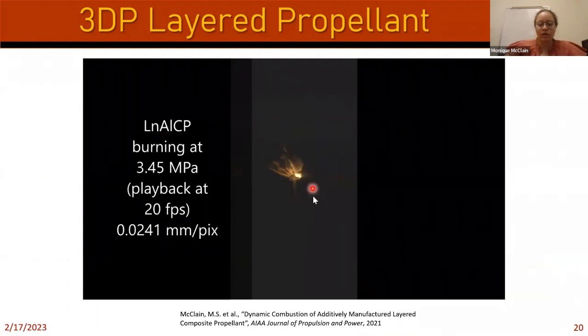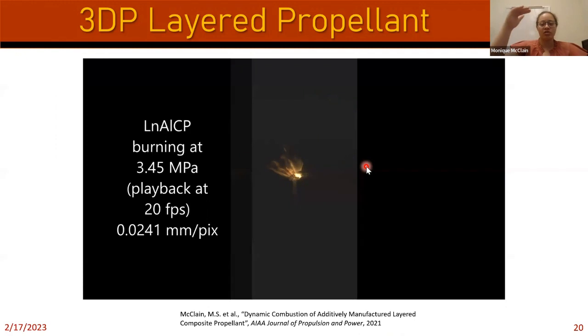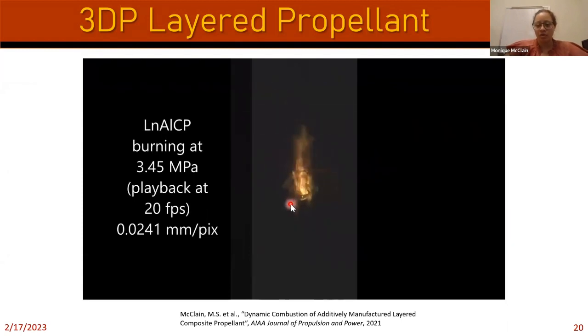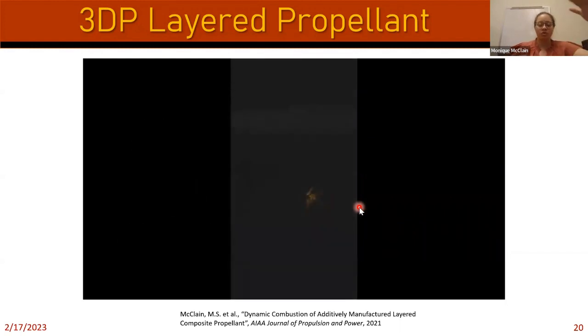So I'm going to show a layered nano-aluminum propellant. Typically, if it was not layered, so let's say it's just ammonium perchlorate, what should happen when you burn it at high pressure is that it should ignite and then burn flat or linearly. But here you're going to see something different. Here we ignite it, and then over time, you'll see that there's some sort of burning surface area developing. So we develop this V shape that eventually becomes pretty stable at some point, right? It doesn't really increase anymore. So we really want to understand, how long does it take from ignition to go to this V shape? What is the length of that V shape when it gets stabilized, and quantify other characteristics.